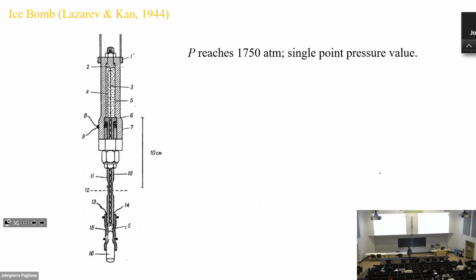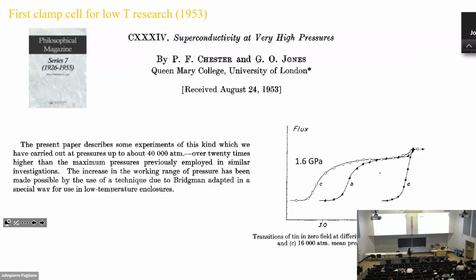So the next improvement, they use the so-called ice bomb. The idea is, instead of using helium to squeeze the sample, what if you put water there? At a lower temperature, of course, water is going to freeze. And we know that when water freezes, the volume actually expands. So that will squeeze your sample. With this setup, you can reach a lot higher pressure. However, you only get one single point. There's only one pressure for each experiment. That's how people did it.